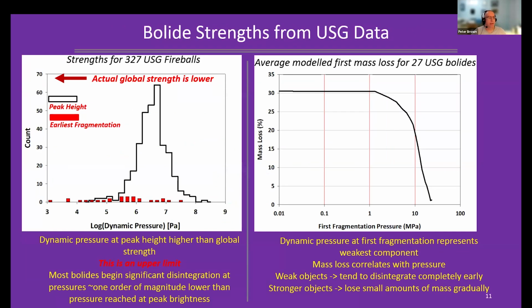Okay, so to cut to the chase, when we measure the dynamic pressures from all of these fireballs, 327, at peak brightness, we get a distribution that looks like this: these things typically get up to a few megapascals in pressure at their peak brightness. But that means that their earliest fragmentation is earlier. And the red bars here are a subset of about 30 fireballs for which we were able to make detailed models to match the light curves. And we find that they typically fragment at a few tenths to maybe up to a megapascal of pressure.